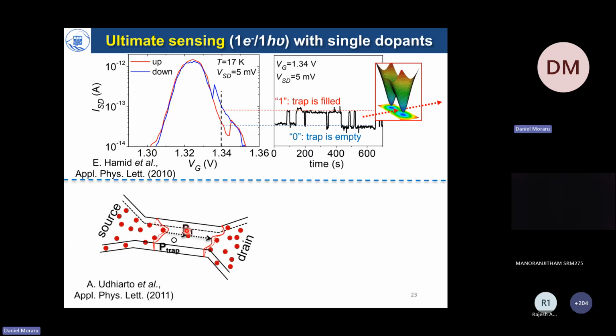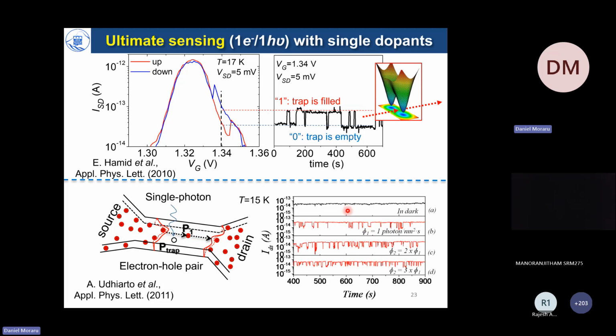We could also use these devices under light irradiation because every single photon absorbed in this channel converts into an electron-hole pair. Now, if you have traps nearby, the electrons can be captured by these traps, and we can actually use this single electron tunneling current to sense this kind of traps. So if you compare the time dependence in dark with the one under light illumination, here we use the visible light, we can see that there is a clear dependence on the photon flux in terms of switching of a current, so-called random telegraph signals. So this kind of dependence indicates that the number of photons influences the number of electrons trapped, which subsequently influence capacitively the charge flow to the main dopant. Again, this is another APL around that time. So this was our initial statement.